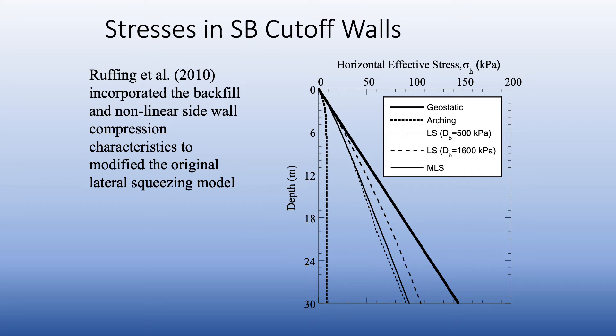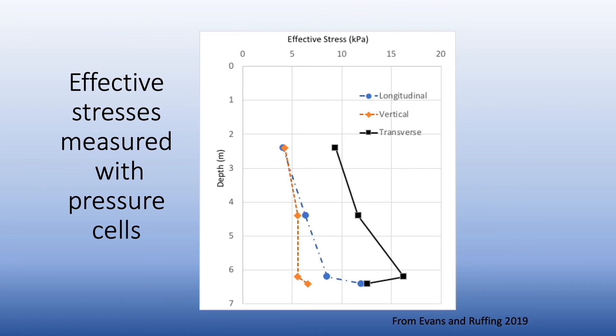The modified lateral squeezing model is shown for both the mean lateral squeezing stress and a range of compressibilities for the backfill, alongside the geostatic stress, which is much higher. Of course, all of these are simply model-based calculations. With funding from NSF, a slurry trench cutoff wall was built and instrumented to measure the in situ stress directly.